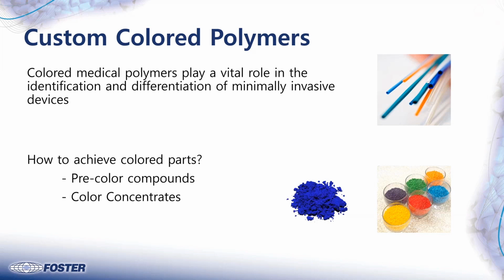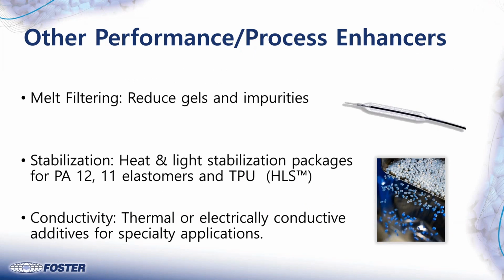So we can kind of dial in some of the properties of the raw polymer by going through a blending and melt purification process before it gets to your extruder. Our extruders range from I think 12 millimeters to 60 millimeters. So we could do the melt filtering on a larger twin screw extruder with a lot of torque. And some of these polymers require a lot of torque to melt and push through the extruder. We can homogenize that, kind of optimize the melt flow so that when it gets onto your smaller extruder, which might be 8, 12, 14 millimeter extruder, you could actually extrude it.